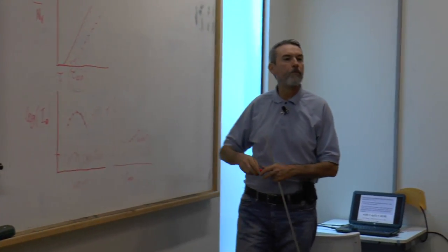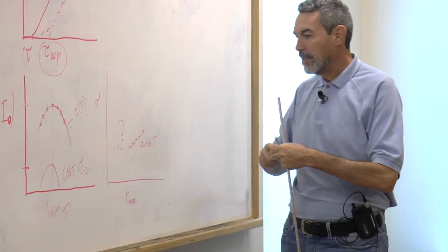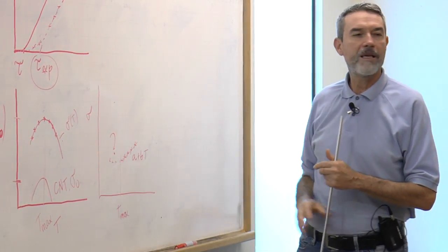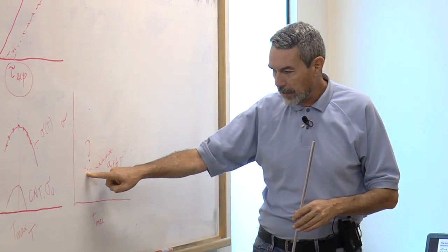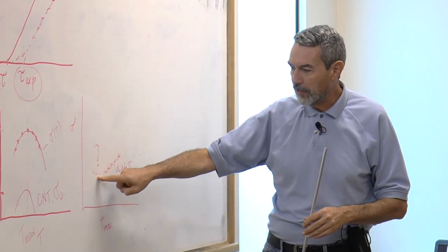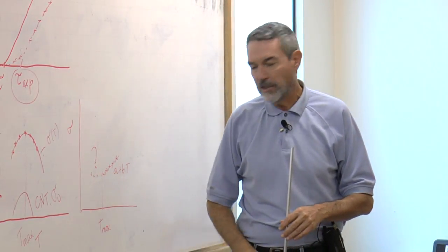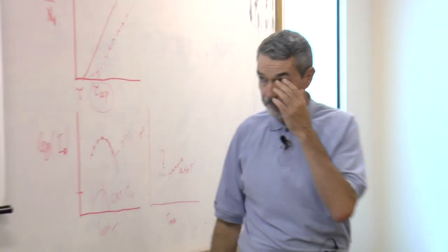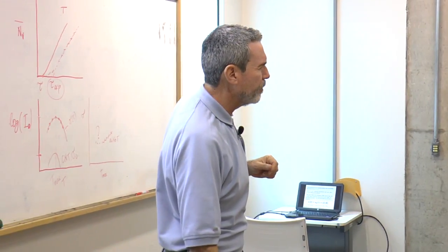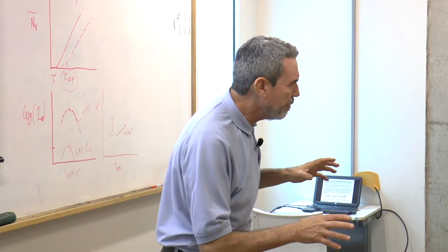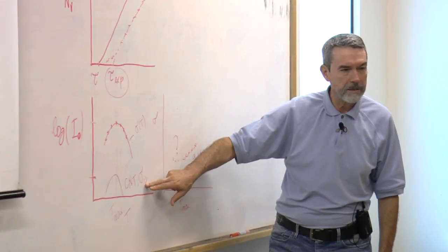If you recall the break that I mentioned to you, even in the sigma, there is a break in this sigma. Okay, I can force fit, but the temperature dependence of sigma is very strange. It's okay above Tmax, very strange below Tmax. I'm not sure if I made this clear to you. The overall summary is this. Classical nucleation theory is a constant sigma.